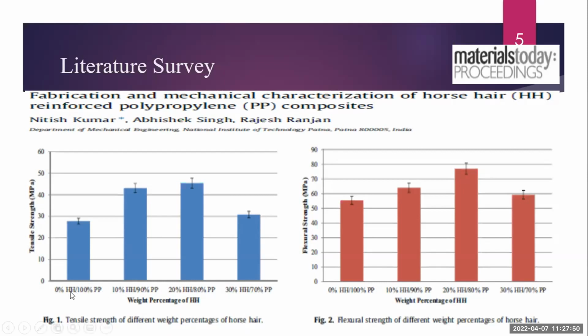What they did was vary the percentage of horsehair and polypropylene. In the first mixing, you can see that they fabricated a composite based only on 100% polypropylene. It means they did not mix any horsehair into it. After that, they formed the next sample in which they mixed 10% horsehair into 90% polypropylene. In the same way, in the third sample, they mixed 20% horsehair and 80% polypropylene. And in another sample, they mixed 30% horsehair and 70% polypropylene. When they tested these samples, they found that the best mixing ratio was 20% horsehair and 80% polypropylene. This is the optimum composition.